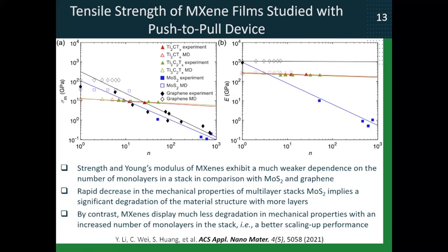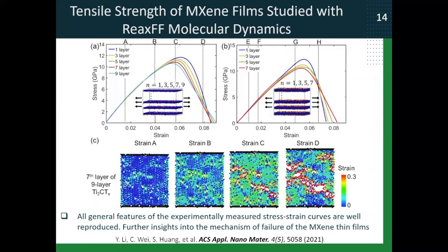And then again, we used modeling to understand the atomistic details of what happens in these stacks. And now we used ReaxFF molecular dynamics, and we modeled the stacks of MXene monolayers with different number of layers, two different MXenes. So this is titanium 2C, this is titanium 3C2, different number of monolayers. And again, we can calculate stress strain curves. And what was interesting is that these curves demonstrated pretty much same shape and same behavior as what we observed in experiment. These are experimental curves. These are our calculated curves.